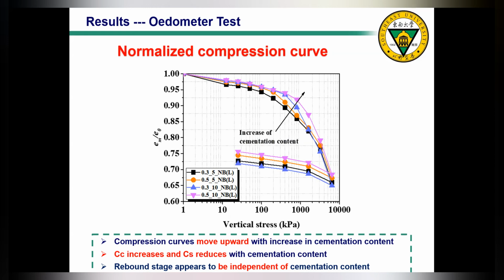And accordingly, if we look at Cc, the compression index, and Cs, the swelling index for this part, with the increase in cementation content, Cc increases and Cs reduces. And finally, if we look at the rebound state, interestingly, even if the cementation content is different, the slope for this part, or we can say Cr, the rebounding index, is very similar among these cases. It means that the rebound state actually is kind of independent of cementation content. And this can further prove that at this stage, the interparticle cementation has been fully broken.